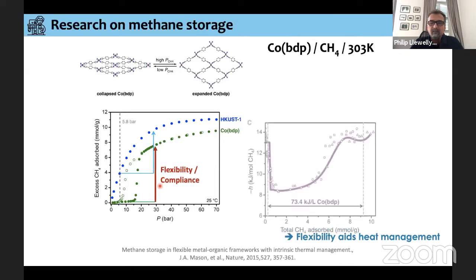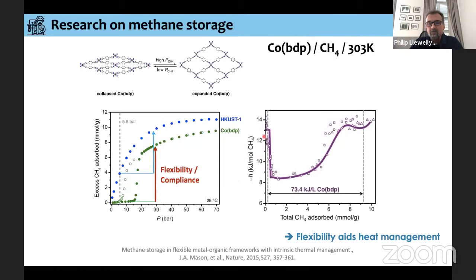The added thing is when we look at the energies of adsorption here. These are the energies of adsorption for methane on this material, so the enthalpies here, as a function of methane adsorbed here. The initial adsorption is carried out at around 13 kilojoules per mole. But as we go through this pore opening, we can see a decrease in the energy here before a re-increase as we get to higher loadings.